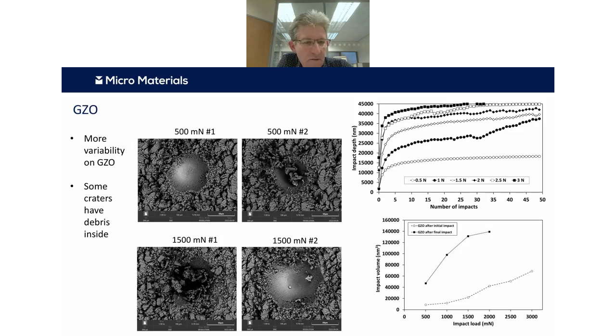And when we perform the same tests on the gadolinium zirconate, what we can see here is, instead of the smooth curves that we saw on the yttria-stabilized zirconia, much more jagged curves in many cases, as you can see on the right. What appears to be happening is that material is falling down from the sides of the crater into the impact crater during the test, and that's what's causing that. If you look at the micrographs on the left, you can see a couple of examples, both at 500 millinewtons and at 1500 millinewtons, where the craters either have debris within them or not. So there's a lot of variability, and this therefore leads to more variable impact volume data as well.